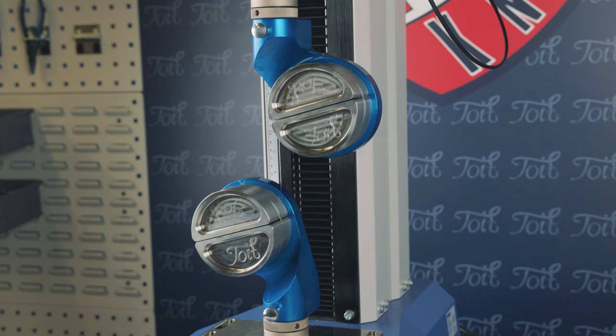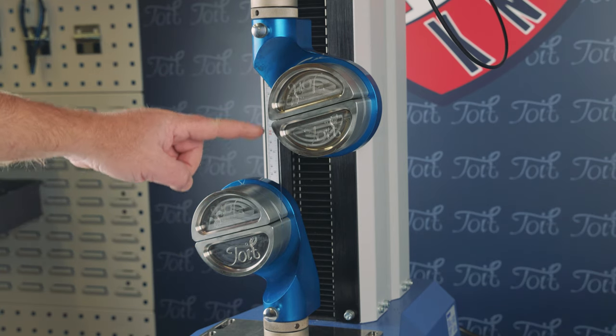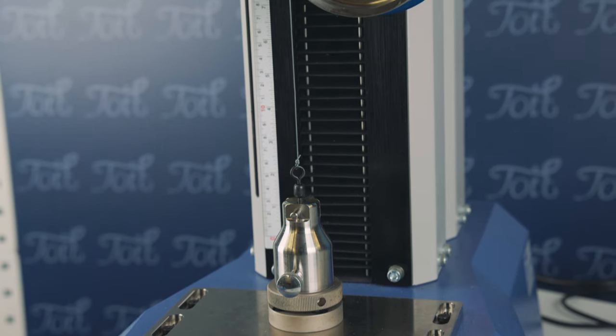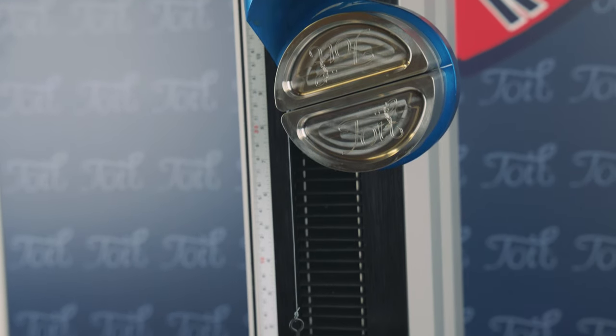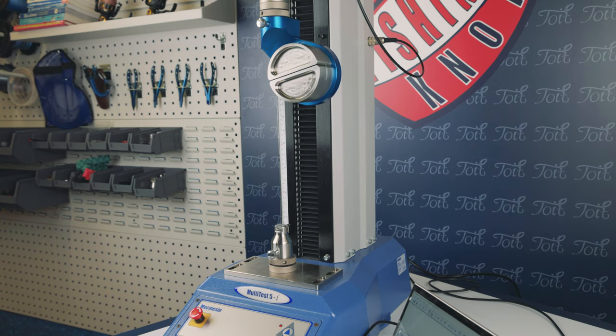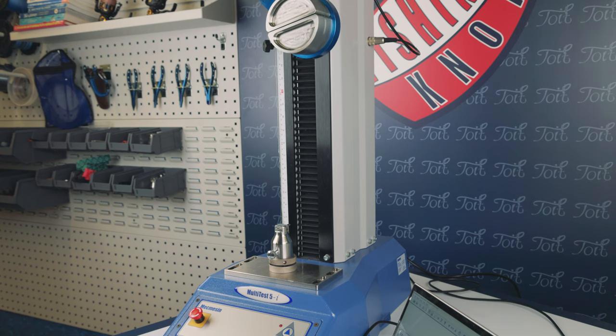So how good was that? It's definitely actually off the scale. In fact it was so good it superseded the actual line strength in a few categories. How is that even possible? Well, if you compare the test sample lengths: an ordinary line-to-line test specimen is approximately 750 millimeters long; a regular terminal knot test line is approximately 600 millimeters long; and on our Bimini twist the single piece of line is approximately 400 millimeters long. There will be fewer defects or manufacturing imperfections in a shorter piece of line, hence the strength is slightly above 100 percent in some line categories.